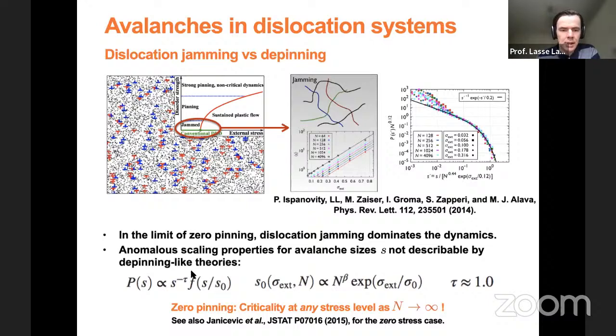the cutoff of this avalanche size distribution, which is a power law in general, has a cutoff. So the cutoff scale of that distribution exhibits some sort of a weird scaling, which is a little bit atypical in the general perspective of these avalanching systems. So there's something called extended criticality, as we like to call it. So this system is in some sense critical for all stresses. But again, this is not maybe the most important thing here.